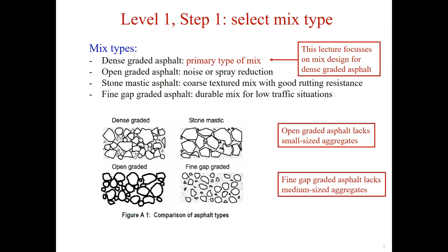A dense graded asphalt mix has a continuous distribution of aggregate particle size and filler and a low design air void content, generally in the range of 3 to 7%.